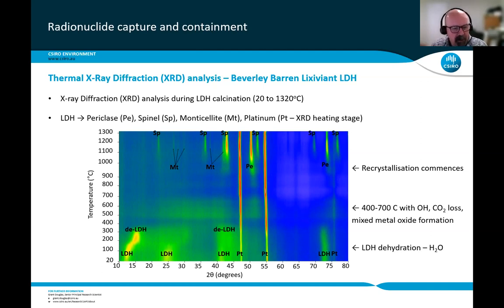in the X-ray diffraction. So if we have a look at the LDH first, the one between about 10 and 15 degrees, as you heat the layered double hydroxide, you get up to about 200 degrees, as you remember from the previous diagram, and you start to get dehydration. Once you get dehydration, you start to move to a smaller interlayer space or a higher 2 theta degrees. So you're effectively just clamping down these layered double hydroxide interlayers as you lose the water.